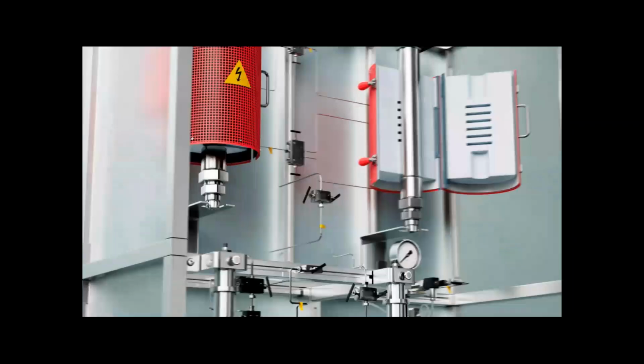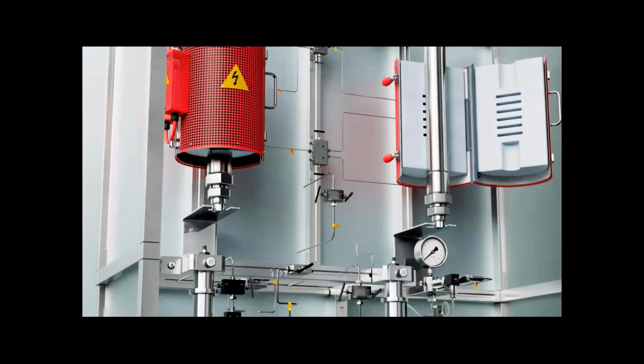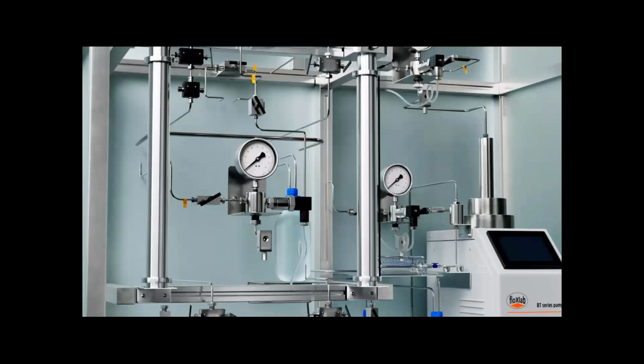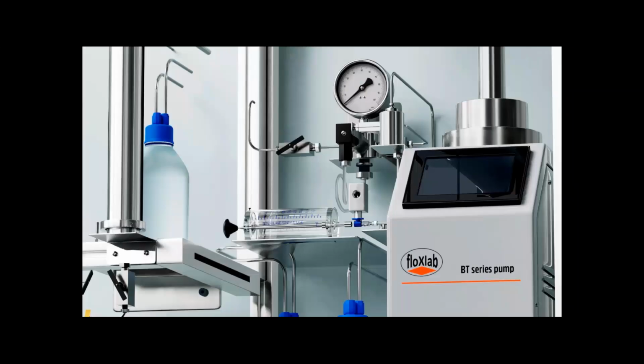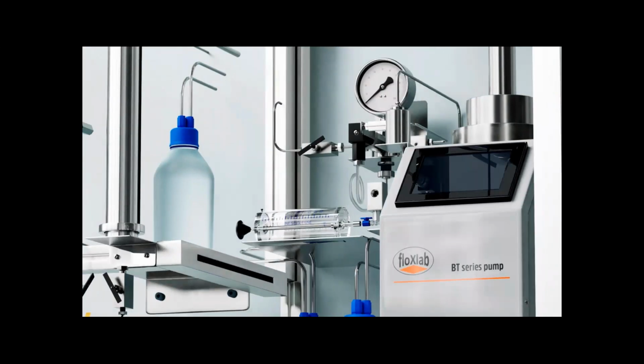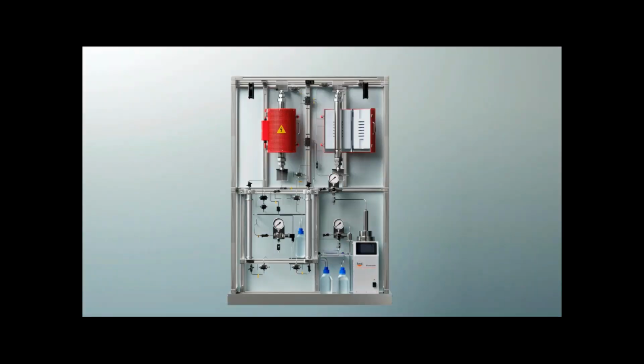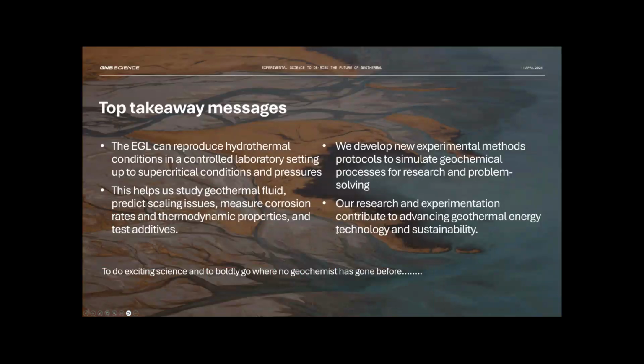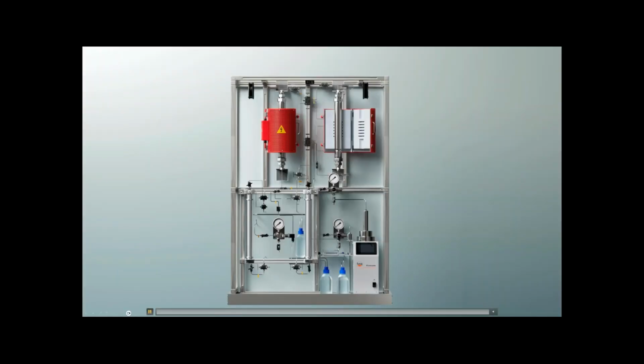And so you can see this here. This is the two ovens. These are the separators that contain the two fluids. That's the back pressure regulator. And this animation shows you the flow path. So you can see the blue fluid is coming out of the first separator. It's passing through the preheater. The second fluid is coming out of the second separator, and they mix together between the two pressure vessels. Then they go through the second pressure vessel, the reactor, and they come down and they're collected in the syringe.